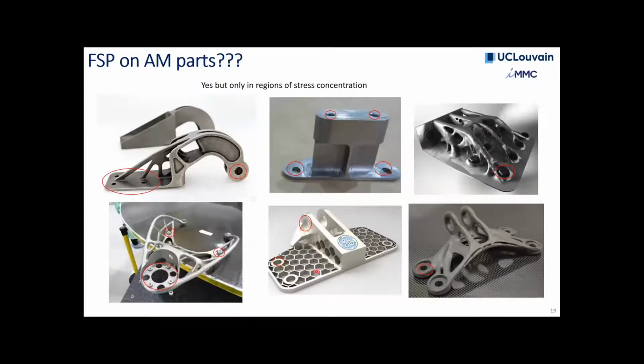You're probably wondering, how can you do this on AM parts? Well, I wouldn't be doing that everywhere, but just in regions of stress concentration, that totally would make sense. And I'm taking here some examples of parts built by AM that you can find in the literature. You can see here that there are regions of fixing the parts to the rest of the structure. And in these regions of fixing, we know that this is regions of stress concentration. So it totally makes sense to make a small tour here, friction stir processing around these, if this can be an interesting post-processing treatment, and I will show you just after that indeed we were improving the fatigue life, so it's an interesting treatment.